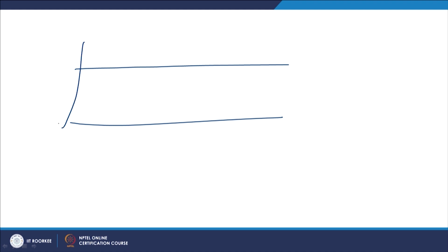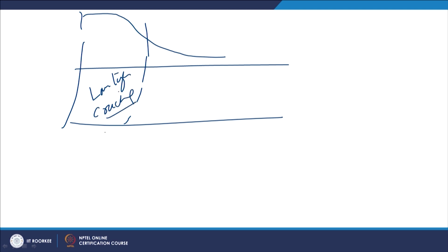So, if we try to notice the variation in hardness in such cases, then the zone next to the fusion boundary will be the hardest, and then hardness will keep on decreasing. The zone where hardness is very high will experience a loss of toughness, and this will show a tendency for cracking and a tendency for embrittlement. So, this is the typical feature of transformation hardening steels, where high cooling rates lead to increased embrittlement, loss of toughness and high hardness.